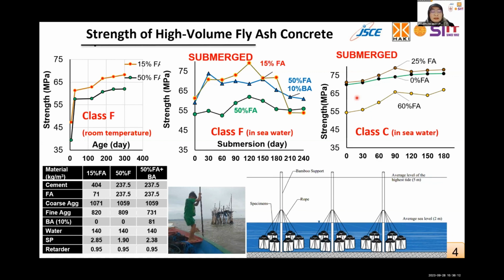We use like 60% fly ash to replace cement, and the strength is still increasing, approaching the specimen with 25% fly ash and 0% fly ash. We believe that rich calcium and silica in the system contribute to more secondary calcium silicate hydrate formations.